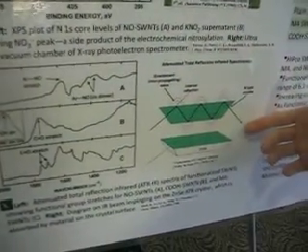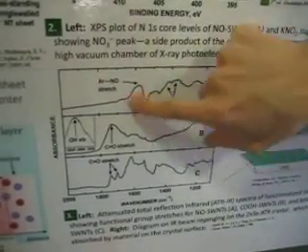We also ran an XPS of the solution supernatant that we had used after the electrochemical cell reaction. We wanted to see specifically the nitrate peak right here, which helps confirm the proposed mechanism for this reaction. We also confirmed these functional groups using attenuated total reflection infrared spectroscopy. These show stretches of the molecular groups caused by the infrared excitation, and these peaks all correlate well with stretches commonly observed for the functional groups of interest, which shows that we do have the right functional groups on these surfaces.